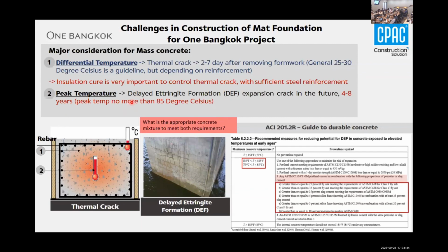And another thing we have to be concerned about is the peak temperature. For this project, we talked a lot about what number we should use for the peak temperature. Otherwise, if we don't consider this, we are going to get what we call DEF in the future. So we tried to get literature, and we sat together and figured out what number we should use. Some recommendations provided that if you use fly ash in the concrete, the maximum temperature can be limited to around 85 degrees Celsius. So we talked about this number for this project.